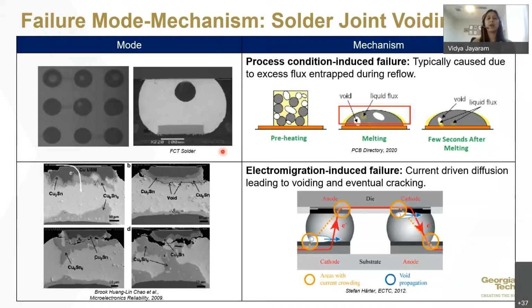They can have multiple causes for the same kind of failure mode. So the first one here, you can see voids that are formed during processing. For example, when you have excess flux that is entrapped, and when this package goes through reflow, the reflow conditions may not be optimum, where it doesn't allow for the volatiles to escape efficiently. So they get trapped inside the solder, and that's how they form the solder voids. This is more of a processing related defect or failure.